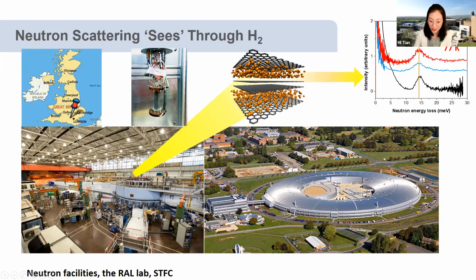So this is, I just brought the laser pointer. This is the neutron facility located in Oxfordshire. You can see this neutron beam is protected by thick concrete to avoid the radiation, and those are neutron instruments surrounding the neutron beam. This is a sample cell I have been working with. The neutron beam can deeply penetrate the cryostat that provides the sample environment, the sample container, and the sample itself, directly probing gas molecules inside the pores.